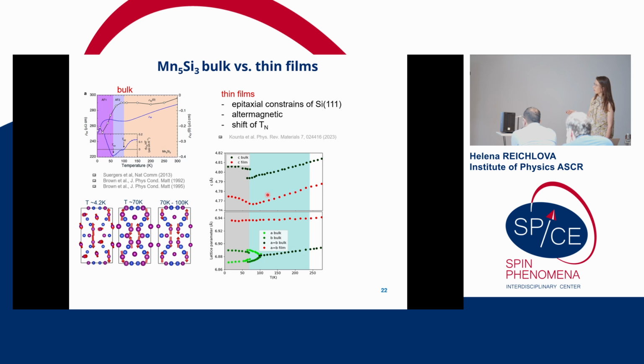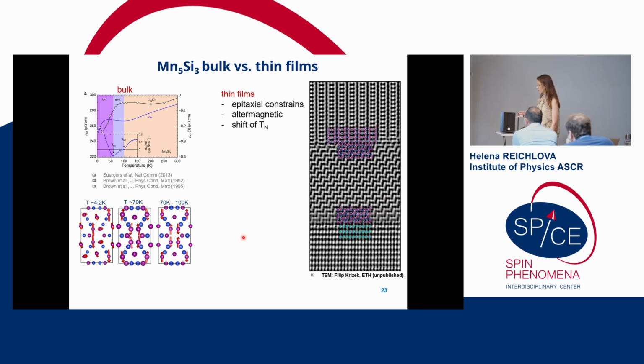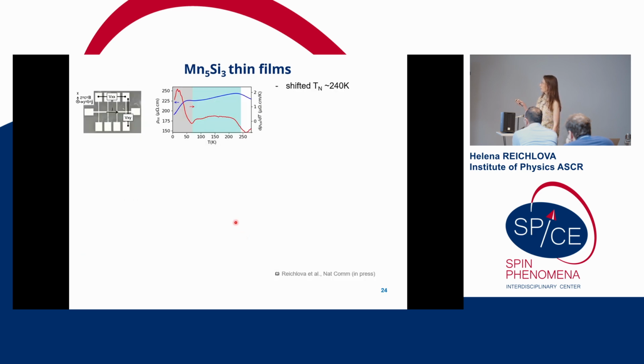So we see that the c parameter, which is the out-of-plane parameter, is changing with the temperature because this is not constrained by the substrate. However, the a and b parameters, which are changing in the bulk compound because there are no constraints from the substrate, are not changing in the thin film. So we have the hexagonal unit cell in the full temperature range. And this we also confirm by TEM results, and this allows us also to see that we have a different phase of manganese silicide, which I will then show in more detail in the following.